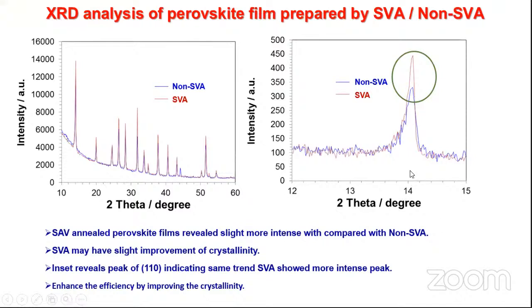When we check the XRD analysis for this sample, the SVA device shows a more intense peak compared with the non-SVA. This means increased crystallinity. The inset shows the characteristic 110 peak of the perovskite. The SVA shows a more intense peak compared to the non-SVA, meaning more crystallinity. Better crystallinity is expected to improve the efficiency.